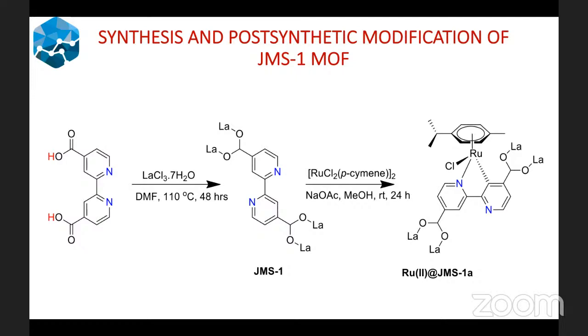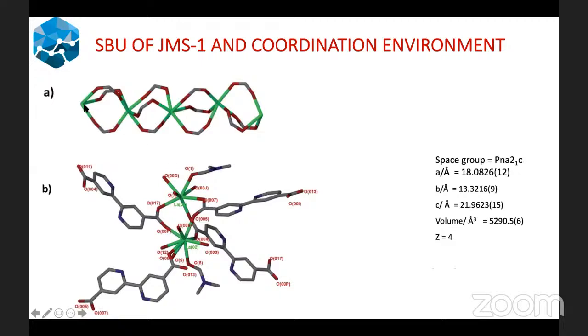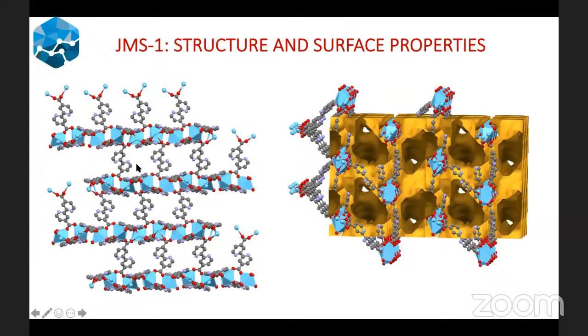So let's look at the crystal structure of this metal organic framework, which was isolated. As you can see, it's made up of a secondary building unit, which was generated in situ, and of course, in the space group Pna2₁c. The most interesting thing here is that you have your DMF coordinated, and your lanthanum has an 8-coordinate geometry, which is very interesting because the moment you remove your DMF, like I said earlier on, you generate open metal sites, which are very important, especially in catalysis and carbon dioxide adsorption. And of course, this is the packing diagram of the MOF.